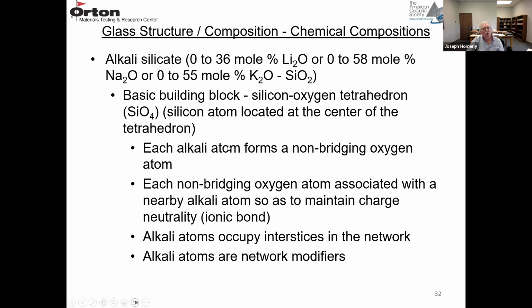You're not really going to see a pure silicate glass in a refractory material. It's going to have impurities. So here's an alkali silicate glass. These are defined as follows: 0 to 36 mole percent Li2O, 0 to 58 mole percent Na2O, or 0 to 55 mole percent K2O. And these are all in an SiO2 glass. So these are 2-component glasses.